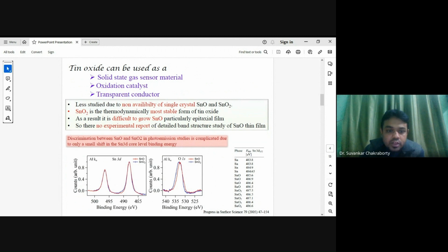So they should show two different binding energies, but as you can see, the blue and red are at the same point, though one is SnO and one is SnO2. So they are showing at the same binding energy. So it is very, very difficult to differentiate between SnO and SnO2 by XPS.